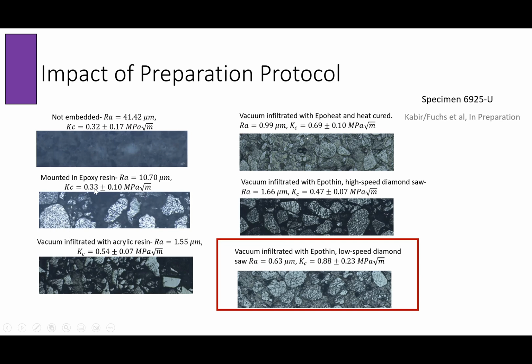Then we can try different protocols, vacuum infiltrated with different types of resin, acrylic resin versus epoxy versus Epothin. Epothin is a really low viscosity resin. And then we really have the final protocol where it is vacuum infiltrated, and then we have a low speed diamond saw in this case. So again, the speed at which we are cutting also is going to have an influence on the property.